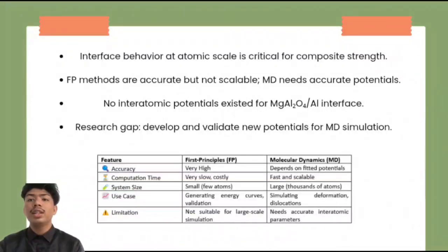One of the central challenges in developing stronger aluminium-based metal matrix composites lies in understanding how the interface between the metal and the ceramic reinforcement behaves at the atomic scale. In this study, the focus is on the interface between magnesium aluminate and aluminium. It is already known that adding magnesium aluminate improves the mechanical properties of aluminium, such as increasing its strength and stiffness. However, the exact mechanisms by which this strengthening occurs, especially the role of atomic interactions and dislocations at the interface, are not fully understood.